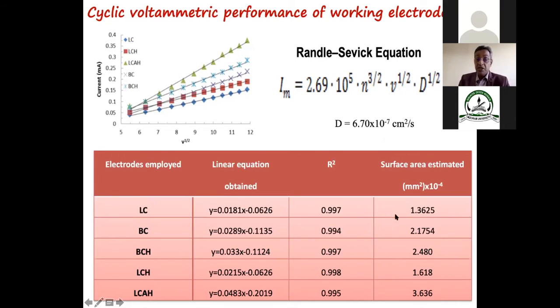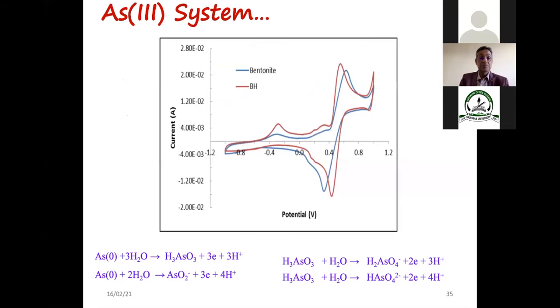Now you see that is the electroactive surface area. Okay, so you can see that the surface area has increased. In the case of LCAH, this material is showing much higher, almost 2 to 3 times higher than when you are using the pristine clay. So a very high electroactive surface area is obtained using the modified material. That means the detection limit that you will be getting is much better, much lower than using simple electrodes. This is the arsenic 3 system that we tried to do.